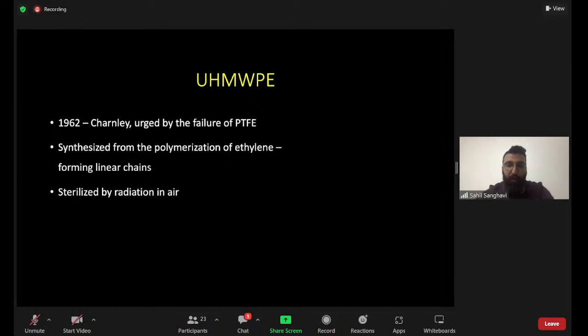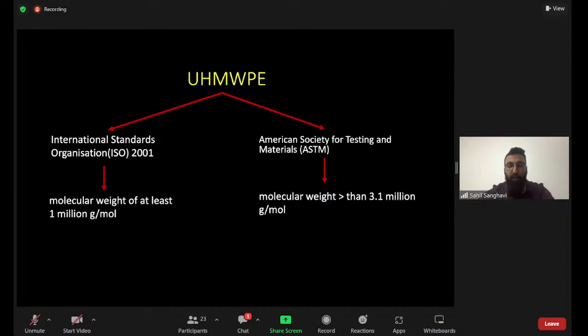So after the disappointment of PTFE, Sir John Charnley introduced ultra-high molecular weight polyethylene in 1962. This is basically synthesized from the polymerization of ethylene, forming linear chains, and it is sterilized by radiation in air. So what is the meaning of the term ultra-high molecular weight? As per ISO standards, it should be more than 1 million grams per mole, whereas as per the ASTM criteria, it should have a molecular weight of more than 3.1 million. So by definition, it is at least 1 million for ultra-high molecular weight polyethylene.